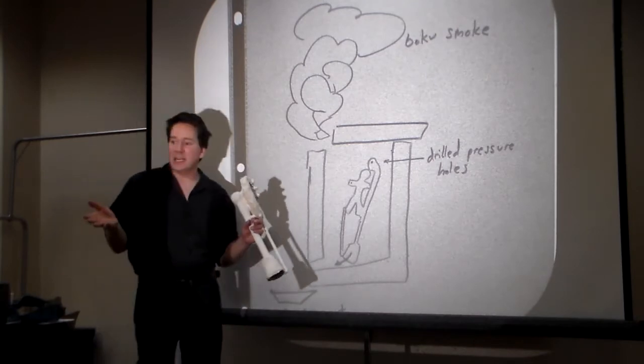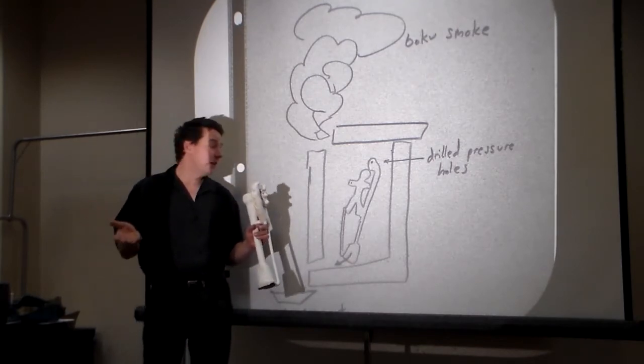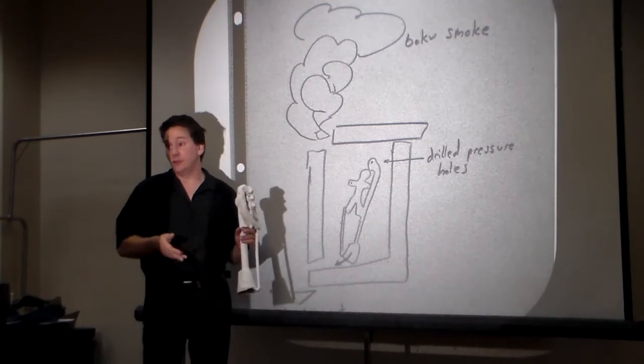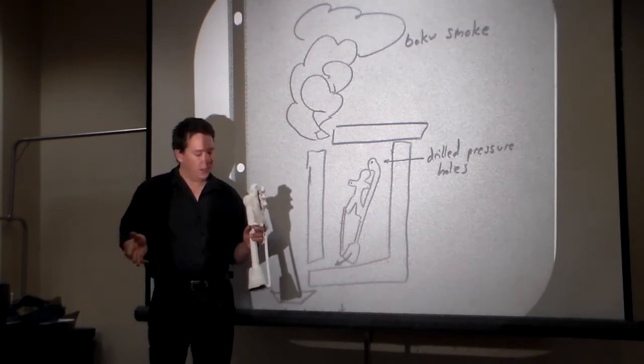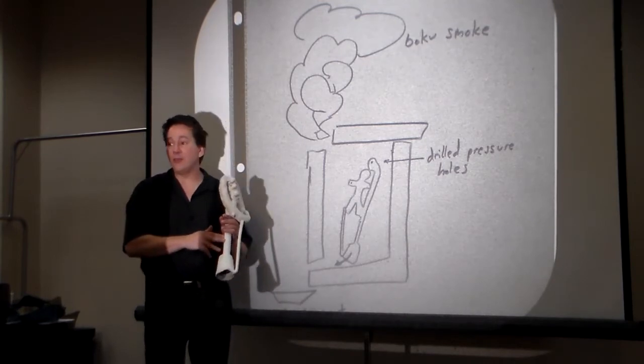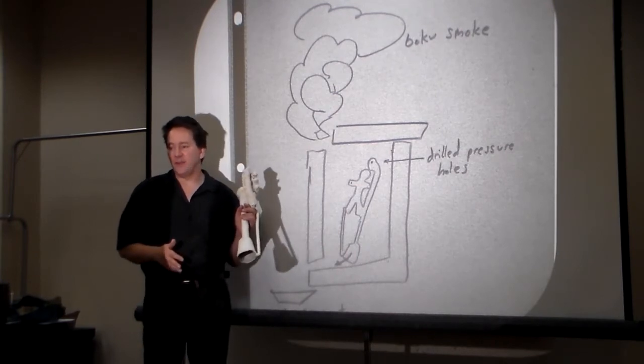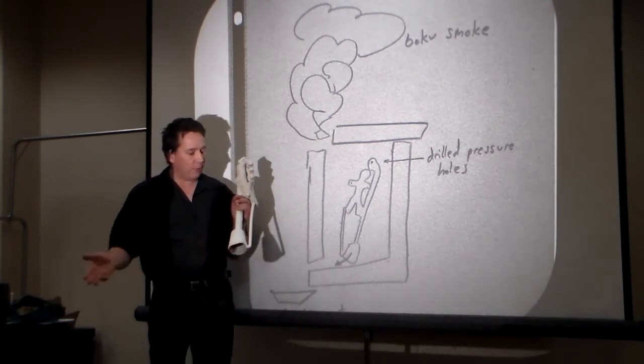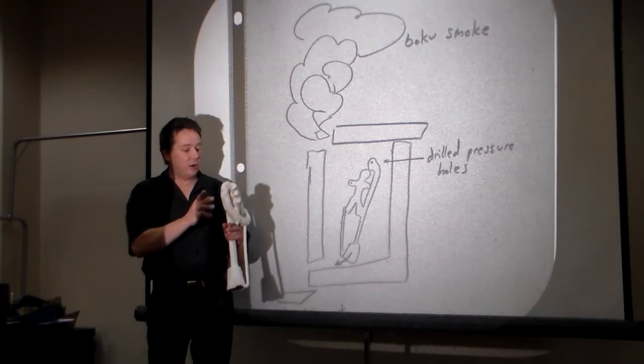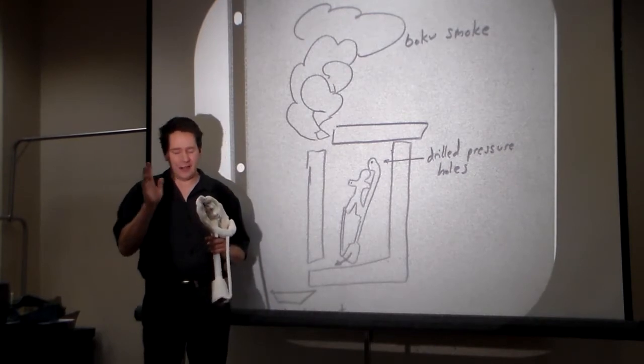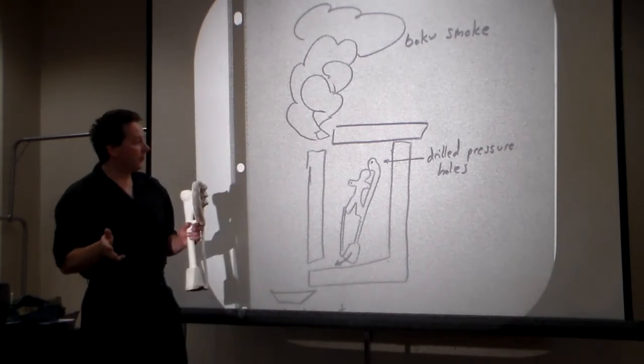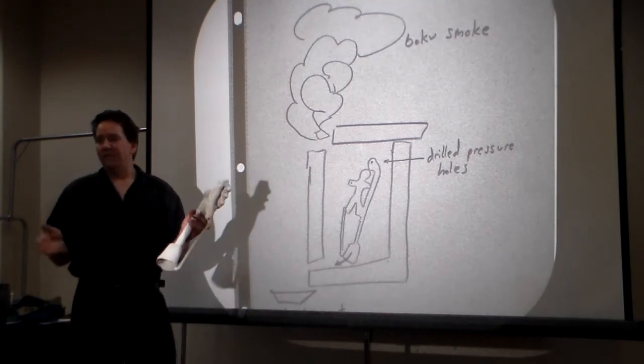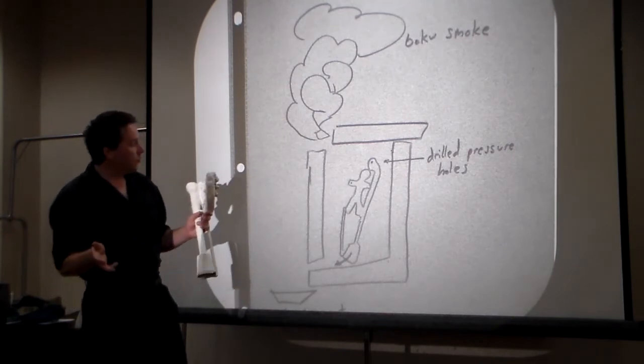For the plaster investment process, it's more casual. You don't need a high temperature. You do need a long, long time to do it. For a piece this size, you want probably 3 days at 1,000 Fahrenheit to slowly melt that wax out, burn it out, and get all the vapors out of the plaster. The ceramic is a lot friendlier. This burnout takes all of 15 minutes. So I'll do that burnout.